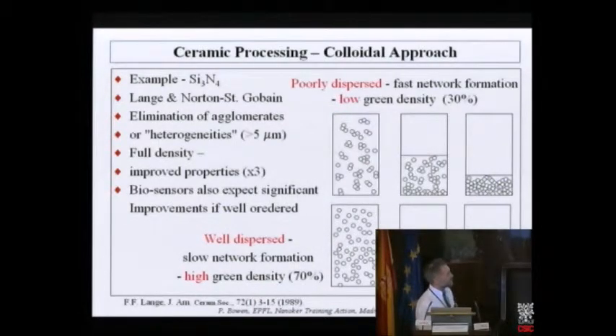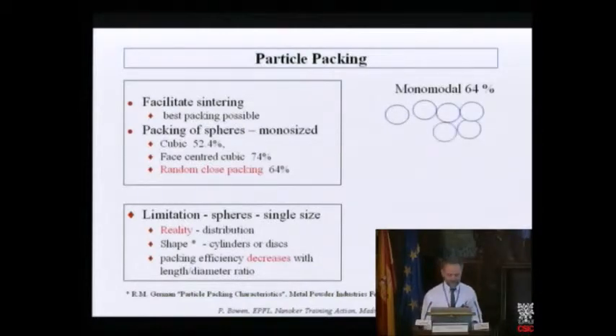F.F. Lange, working with Norton Saint-Gobain, eliminated agglomerates from silicon nitride processing, heterogeneities which were greater than 5 microns. Then after sintering to full density with hot isostatic pressing, they improved the properties by a factor of 3 by taking out these small heterogeneities. This was pointed out by Professor Kaplan this morning. Basically, what we're looking at in all these strength measurements is the size of the critical flaw, and so what you want to do is reduce the size of the critical flaw. If the critical flaw is due to dust in your processing environment, then you can use any nanopowder you like, but you're not going to improve it. And if the nanopowder is aggregated, again, you're not going to improve it. So a key factor is to control the particle packing.